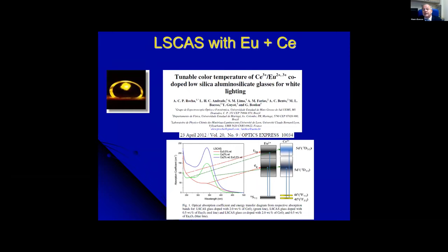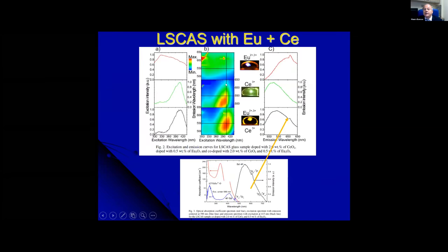We also, of course, mixed europium with cerium. In this paper we showed that we could get better advantage by mixing the absorption bands from europium 3+ and europium 2+ and also cerium 3+ and 4+ to get a good spectrum. And we have the energy levels explained here, this is discussed in the paper. You can see here when you have only europium in the low silica glass, only cerium doping, and then when you put both dopants with appropriate concentration, you can see here an improvement in the emission in the red and yellow region.